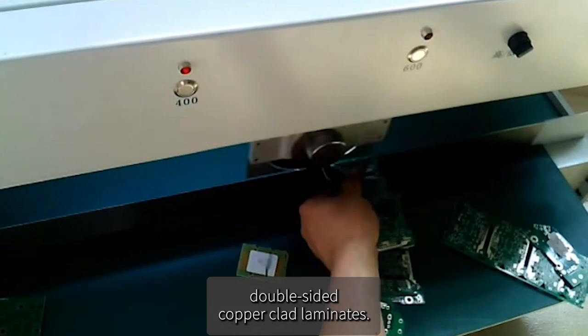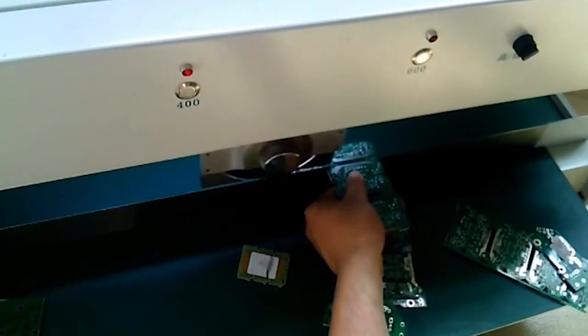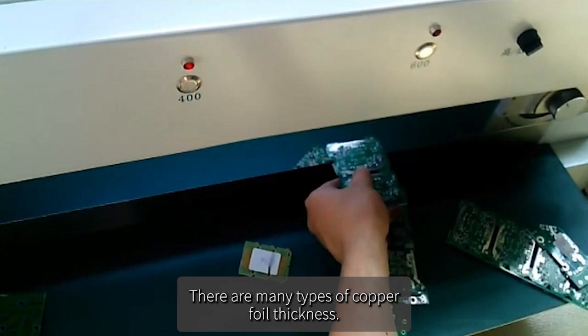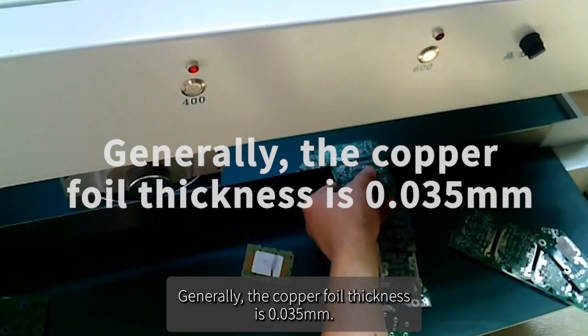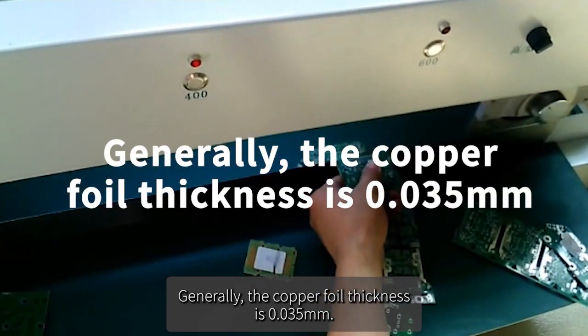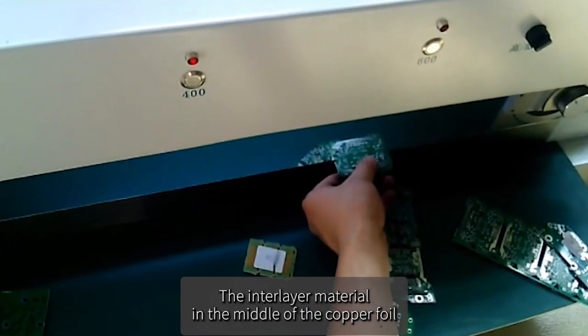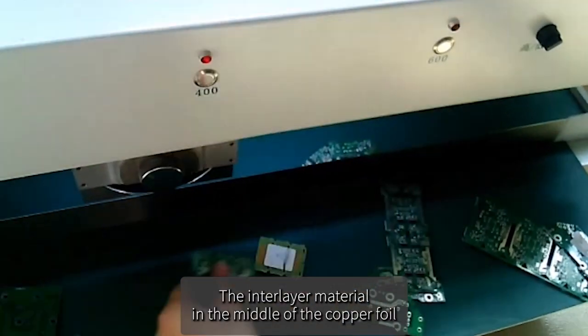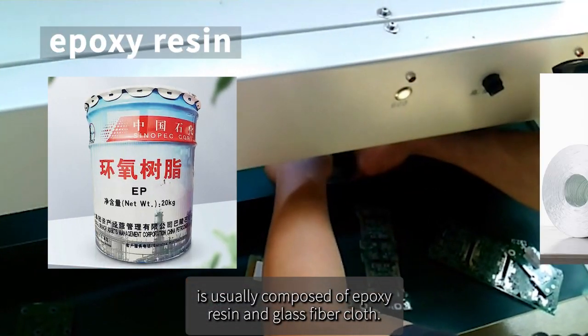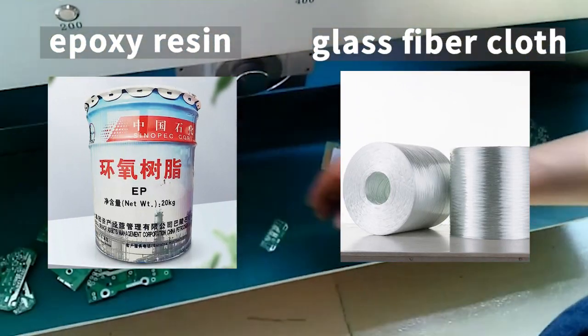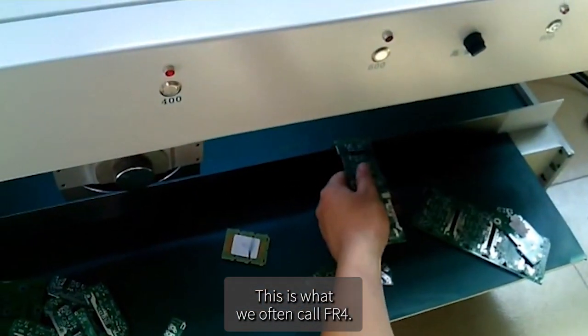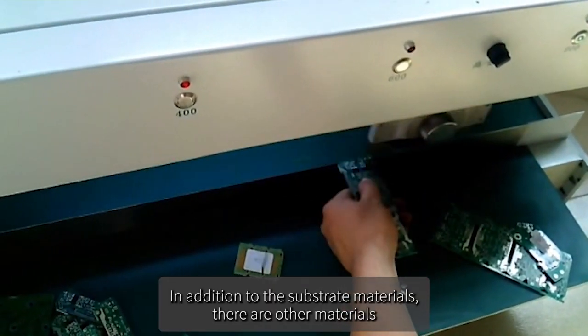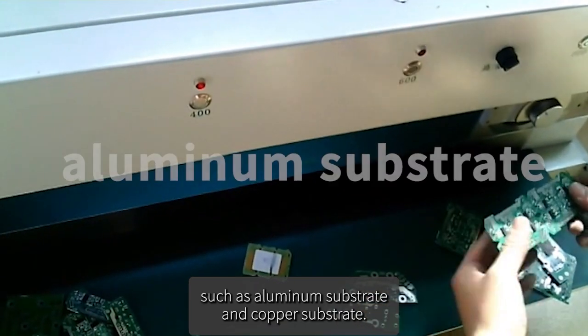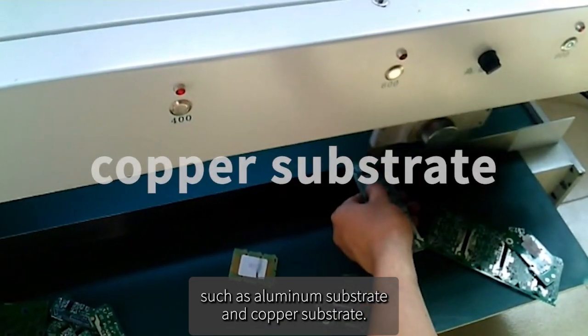Board cutting. PCB boards are generally 2089 by 1246 double-sided copper-clad laminates. There are many types of copper foil thickness. Generally, the copper foil thickness is 0.035 mm. The interlayer material in the middle of the copper foil is usually composed of epoxy resin and glass fiber cloth. This is what we often call FR4. In addition to the substrate materials, there are other materials such as aluminum substrate and copper substrate.